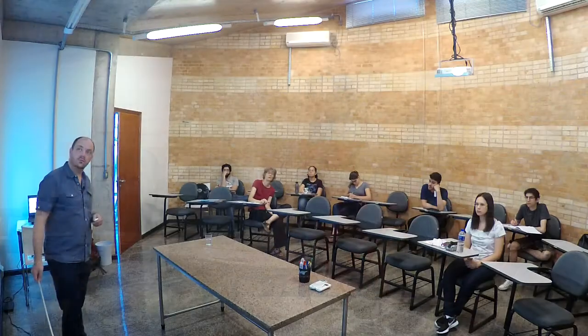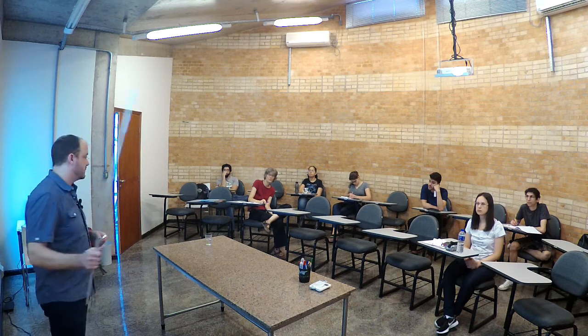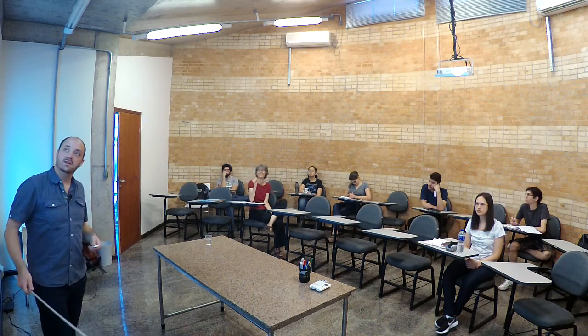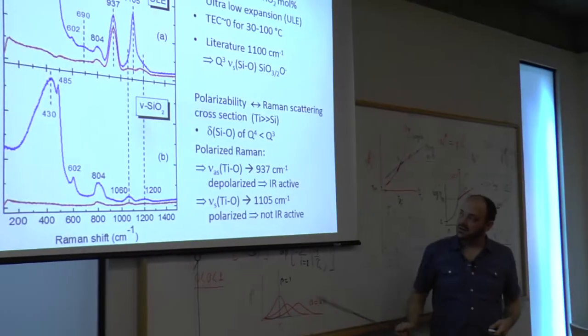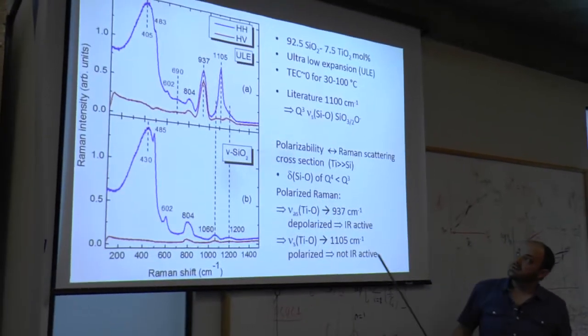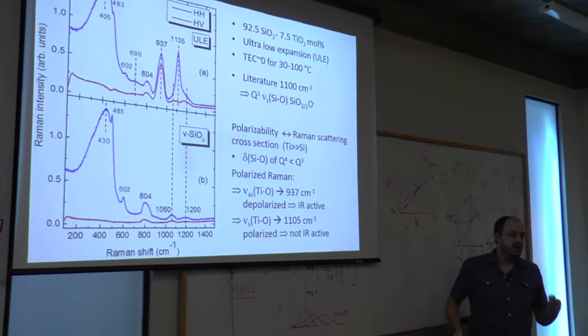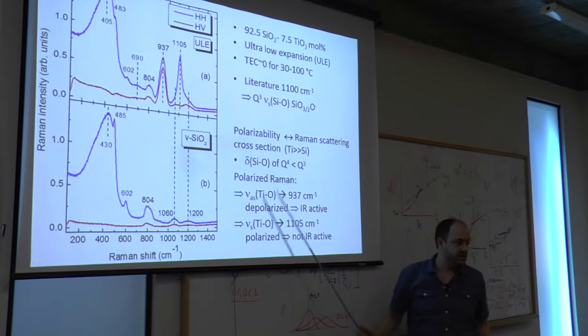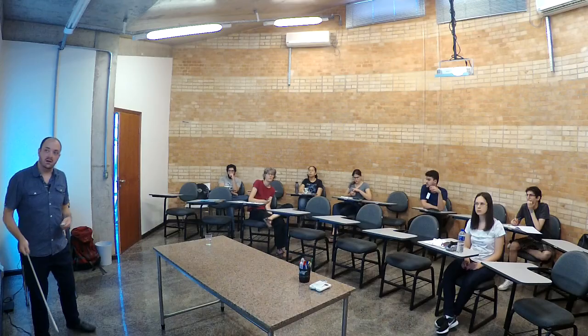I probably didn't give you those slides for Q3 silicate glass, but the polarization is different. It's not as strongly polarized as you see it here. So in the end, that's what you see at the bottom, that both bands, the 1100 and the 900, are connected to titanate. So if you just look at the literature values, you might make this mistake, but actually they're related to this titanium. And once again, this is a nice example where a small amount of something added can really radically change the spectra. So you have to be careful of your interpretation.